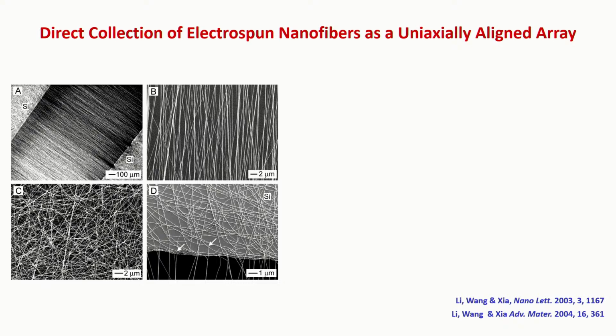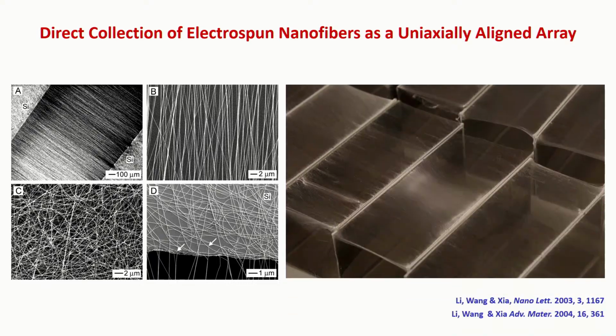And here I just show you this edge. So you can see the fibers do feel the strong stretching force when they're moving close to the edge. The fiber was along this direction, and then suddenly feels the stretching force. They are stretched across the gap. This is the gap over here. And now we can easily generate aligned fibers over long distance by using a very simple device.